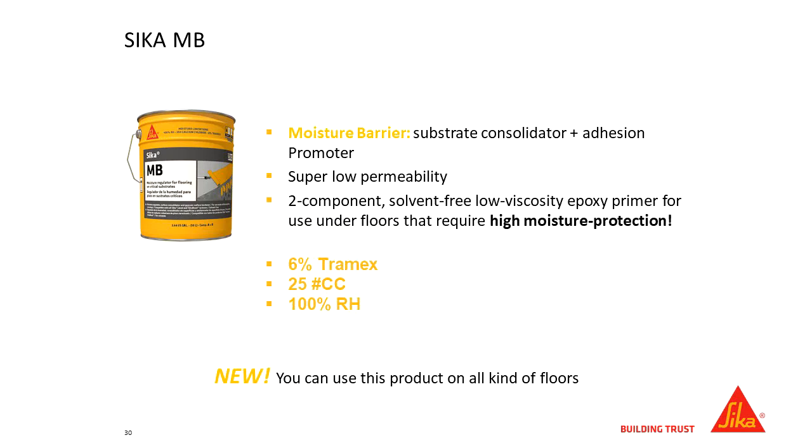SIKA only asks you to remove 50% of it because of that adhesion promotion that you see there on the bullet point. If you remove 50% of that adhesive, and I usually tell contractors, rule of thumb is anything larger than the size of your fist, you want to keep sanding or grinding, scarifying, whatever you're using to take up that adhesive, you want to keep at it until these blotches, for lack of a better term, are smaller than the size of your fist. But what it'll do, because it penetrates down into the slab about 3/16 of an inch, it'll encapsulate that remaining 50% of the adhesive.